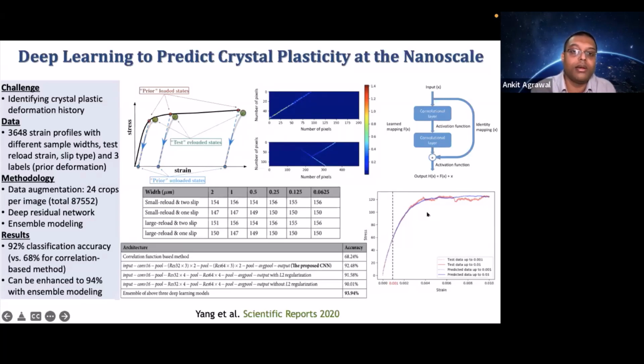And another great thing about this model was that it could predict stress strain curves. So here you see the red is the actual stress strain curve, and then blue is the predicted. So as you decrease the width of the sample, it becomes harder. But this was quite encouraging for us, and the collaborators were very happy with this. Again, more details in this Scientific Reports article.